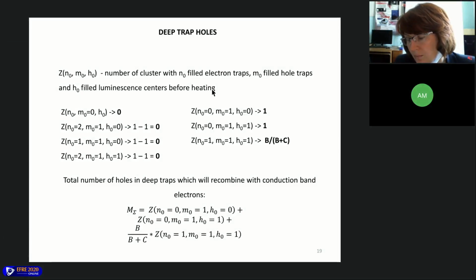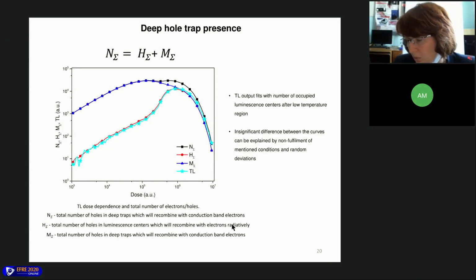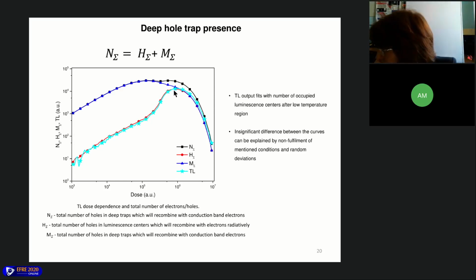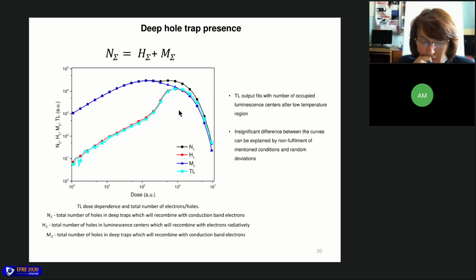Here a similar expression for deep hole traps is shown. The figure shows those dependencies for occupied trapping centers after the low temperature region. The TL curve has several regions with different nonlinearity indexes: linear, superlinear, sublinear, and non-monotonic. It can be seen that the TL output fits with the number of occupied luminescence centers after the low temperature region, since they stand for the number of radiative recombinations during heating. The insignificant difference between the dependencies can be explained by non-fulfillment of the mentioned conditions and random deviations.